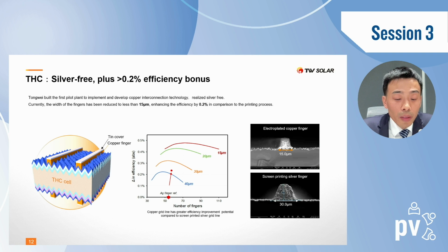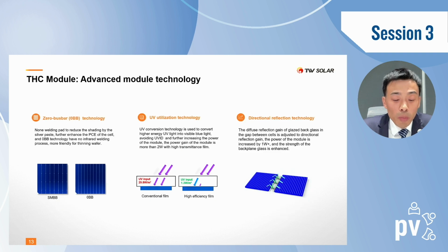Tongwei built the first pilot plant to implement and develop copper interconnection technology, realized silver-free. Currently, the width of the fingers has been reduced to less than 15 micrometers, enhancing the efficiency by 0.2% in comparison to the printing process. Tongwei THC module technology package includes three elements. Firstly, zero busbar reduces welding pads to enhance efficiency and is more compatible with ultra-thin wafer.